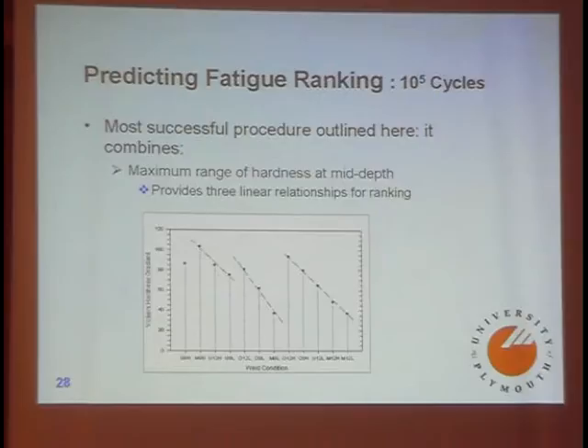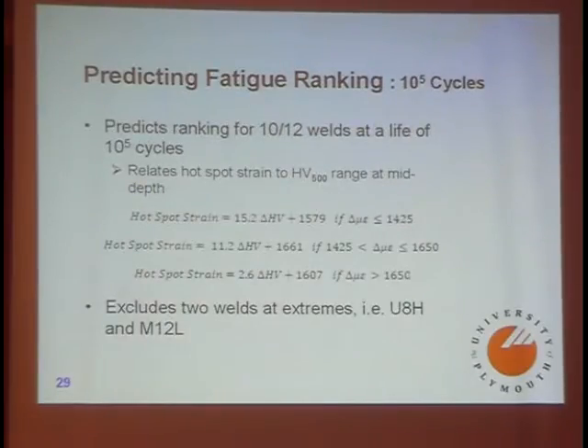And if you take those 3 data ranges, you can then plot them against maximum range of hardness at mid-depth, and you get 3 linear relationships, along with 1 or 2 flyers that we can't predict easily. But you can then predict the ranking from strain and micro-hardness data for 10 out of the 12 welds at a life of 100,000 cycles. And you've seen how scattered this data is. So my suspicion is that this is probably a reasonably fruitful way to try and understand how to take account of microstructural influences and residual stress influences that arise from welding.